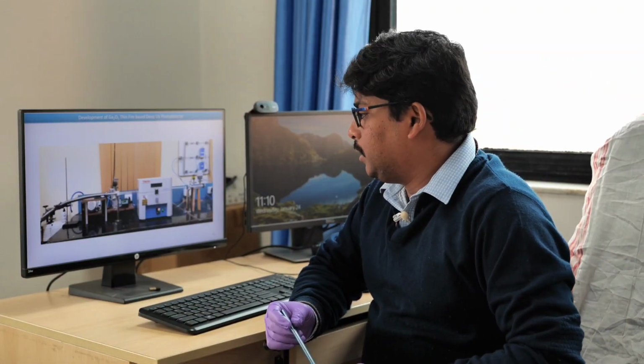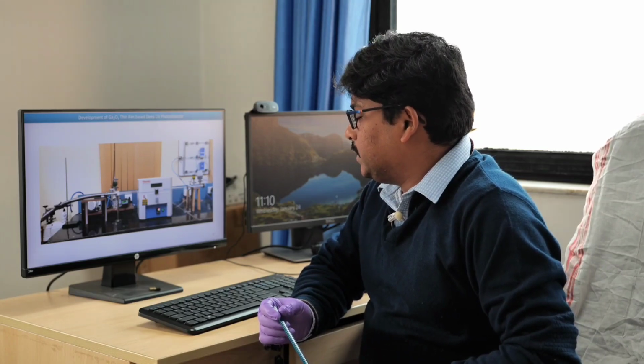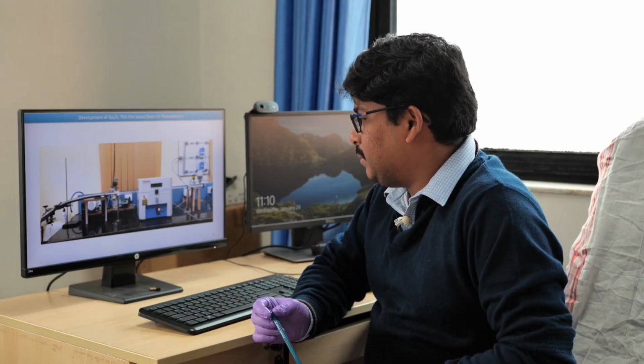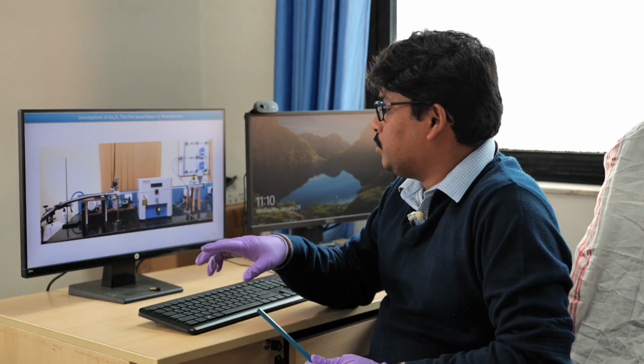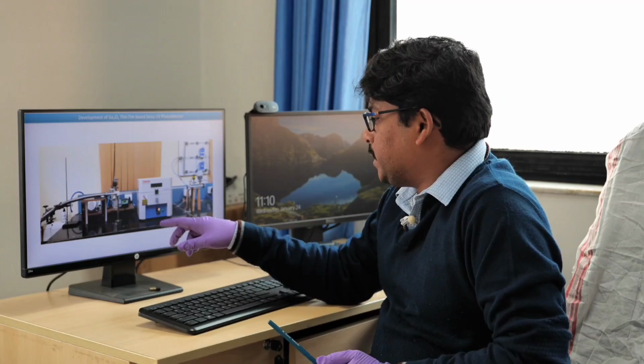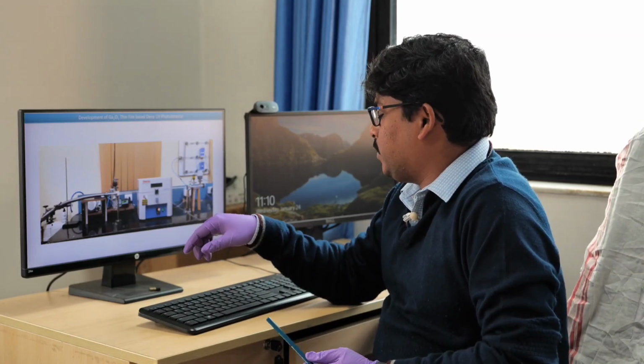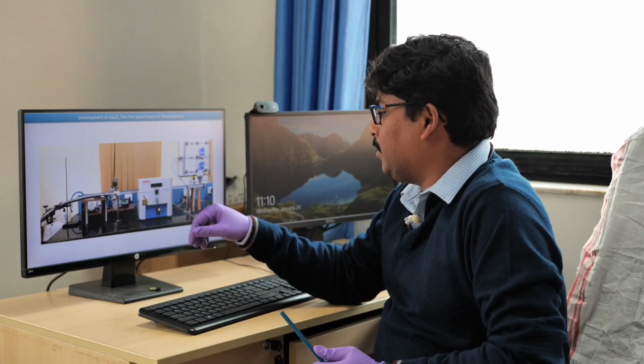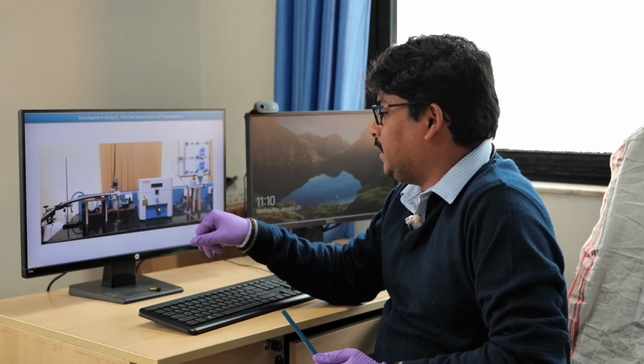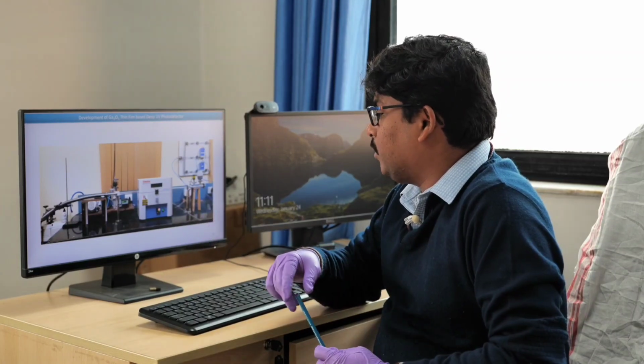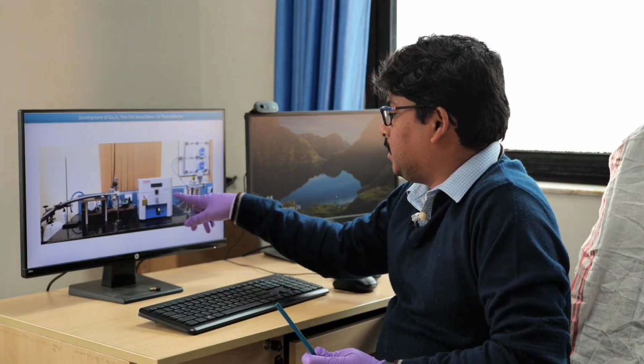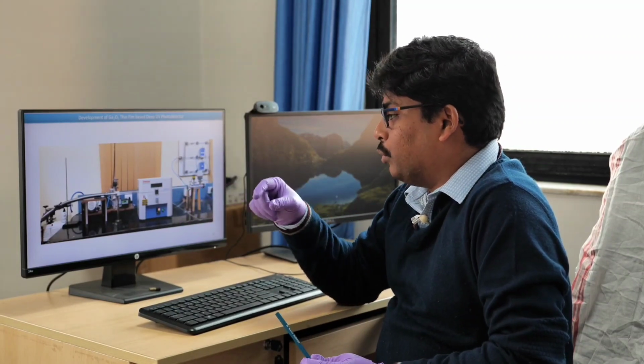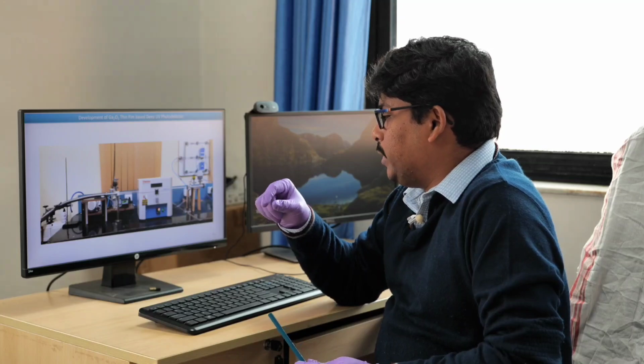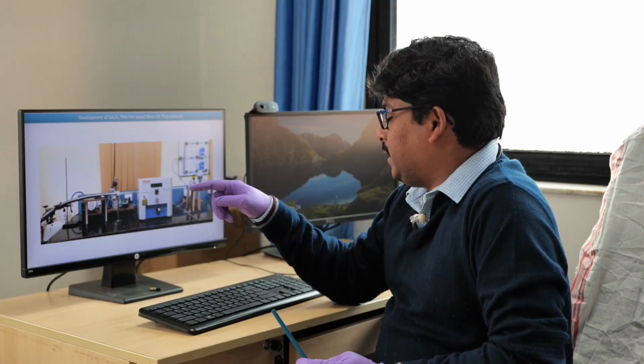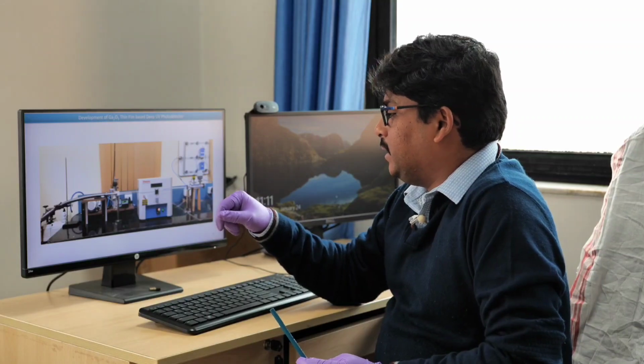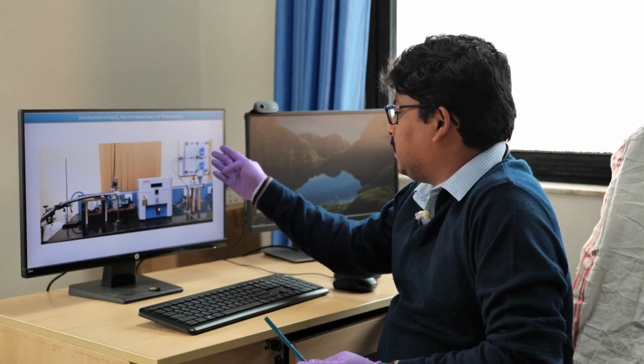So as I just explained, to synthesize or develop this gallium oxide based material, we used this kind of low pressure chemical vapor deposition setup, and as you can see, this is completely customized. Here we bought different components and then assembled them together as per our requirement. Now this is the main furnace. Inside this we have some boats, and on top of the boat we kept the gallium as a precursor, and there is another gas cylinder attached after these MFCs.